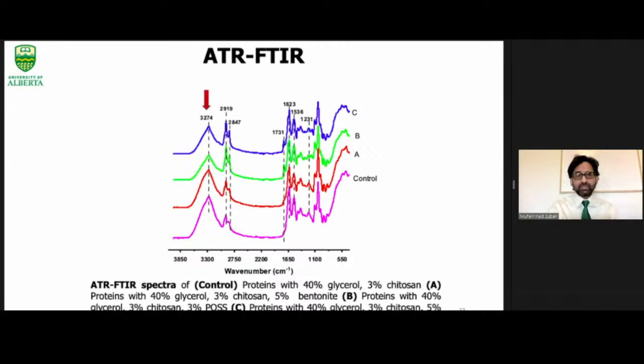The first important peak that is observed at around 3274 wavenumber belongs to the amide A region, or typically belongs to the OH. The second region is the amide 1 region, that belongs to the carbonyl group of the amide. And the third region is called amide 2 region, that belongs to the NH. And then the third region is basically amide 3 region, that is related to the CN stretching and NH vibration of the amide groups. However, one of the most prominent peaks that appeared in case of films containing nanoparticle, that is around 1700, might be the presence of the ester linkage between nanoparticles and the films.